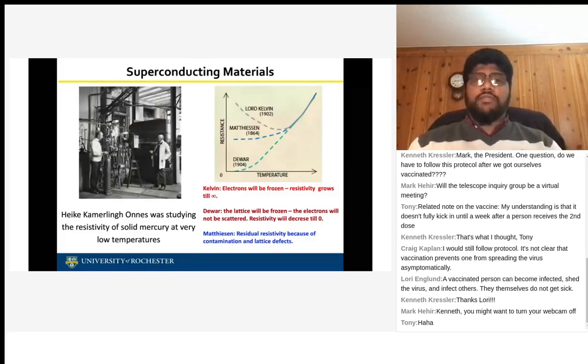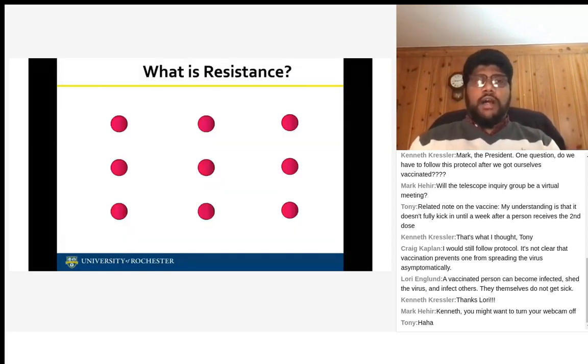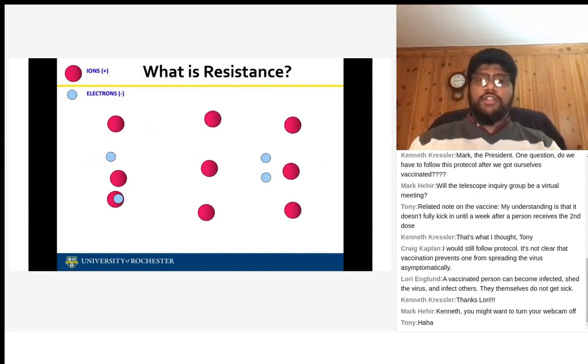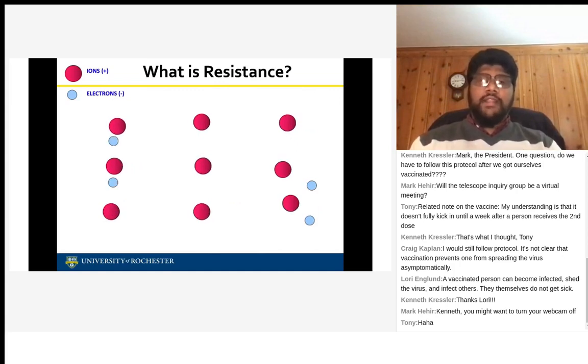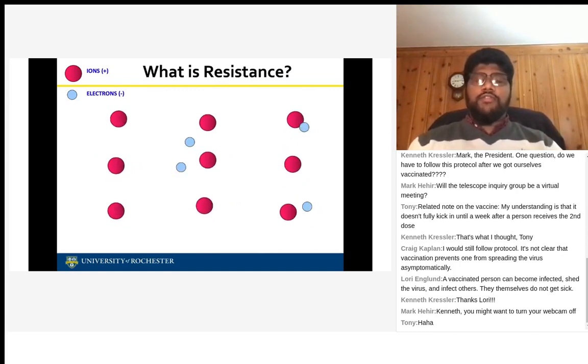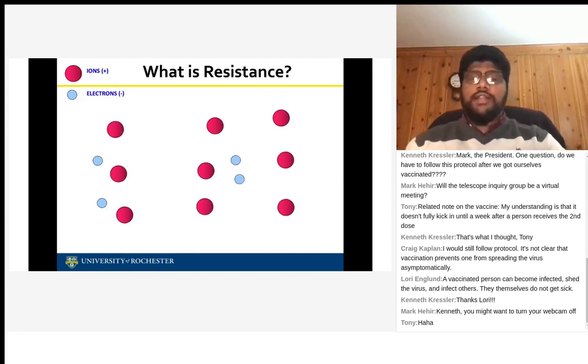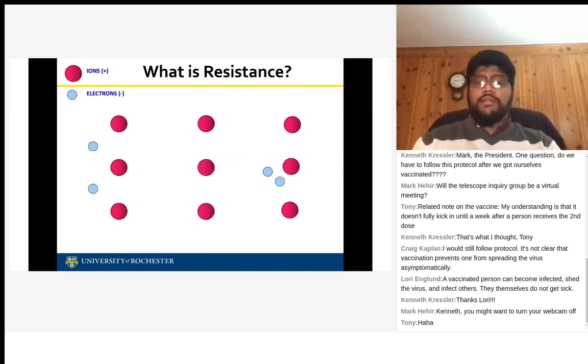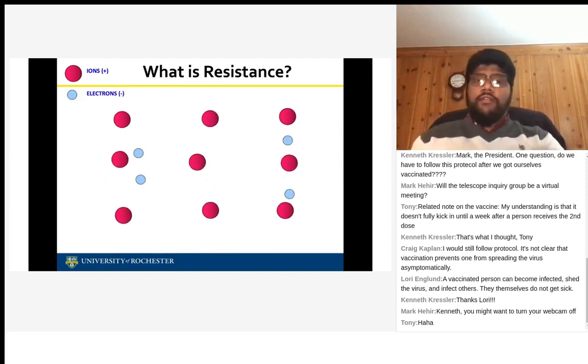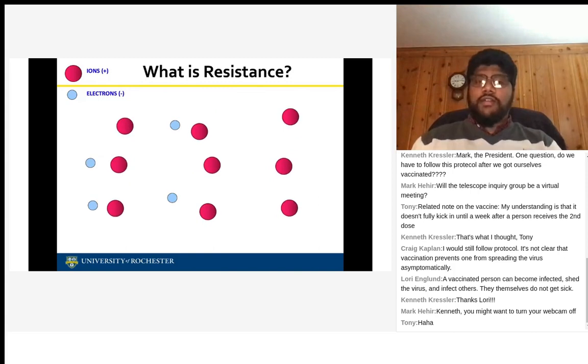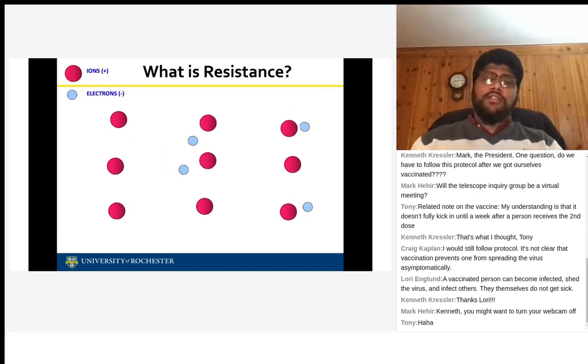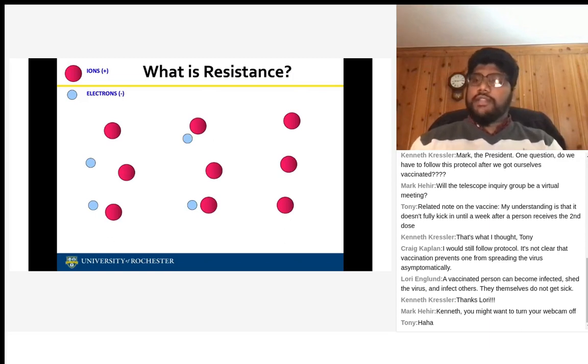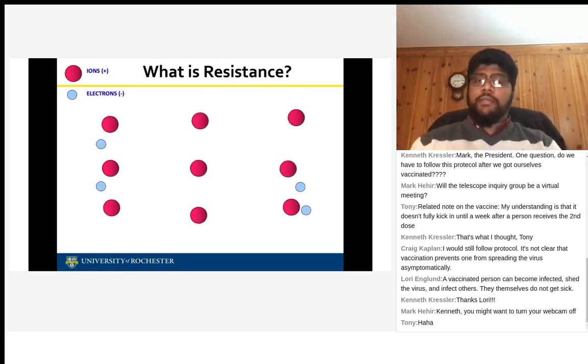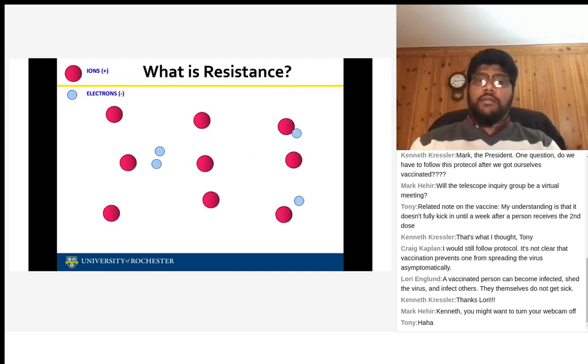As I was saying, the electrical resistance comes from, let's say the red are ions and the blue are electrons. They're vibrating and bouncing off each other and off the atoms, and that causes the resistance, which generates heat, and then you lose a lot of power. But imagine a material where an electron can pass through without any disturbance, without bouncing off each other or even the atoms, going through smoothly and freely. Then you have zero resistance, so you can save the energy that you lose to resistance. Because of this, superconducting materials have become very technologically important.